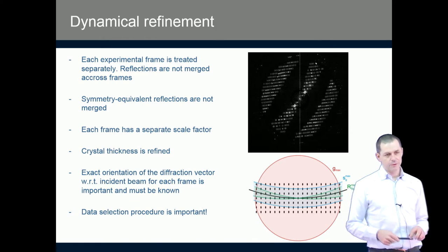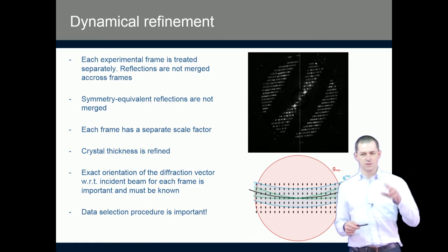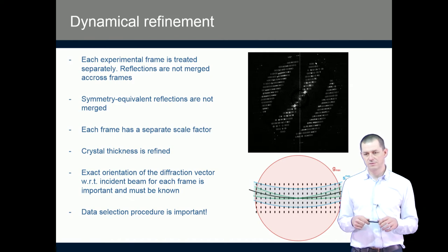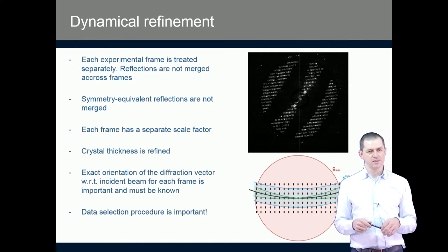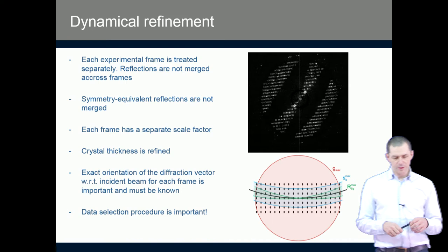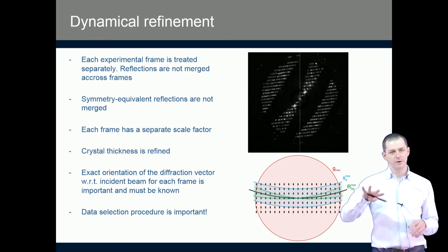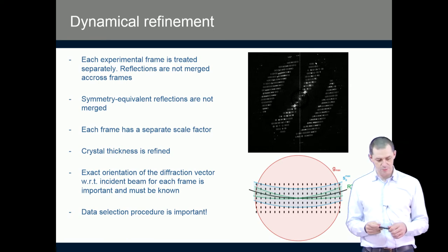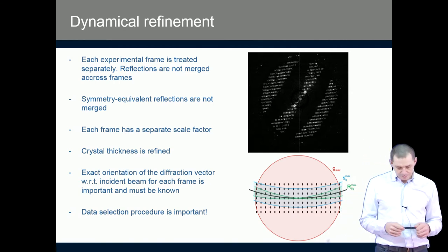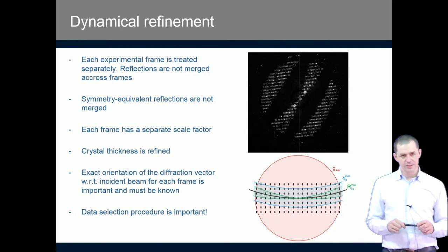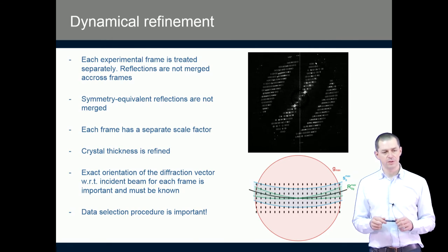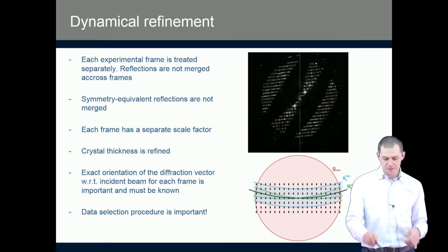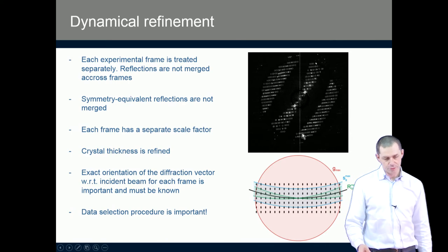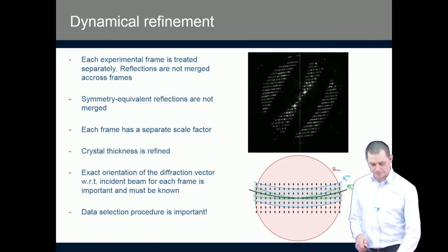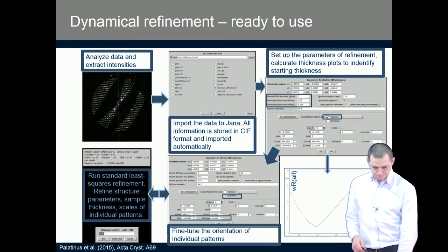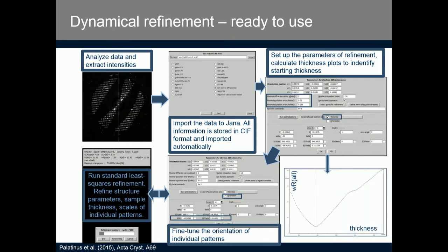We need to refine crystal thickness, because the dynamical effects are a function of crystal thickness and orientation. So we refine the crystal thickness and we refine the orientation of the crystal with respect to the incident beam. And we need to carefully select the data that are used in the refinement. Not all the points in the diffraction pattern are suitable for the refinement. So this is the procedure as implemented in Jana.